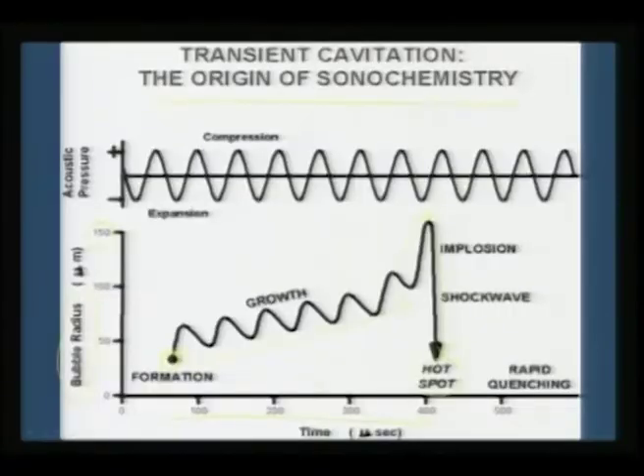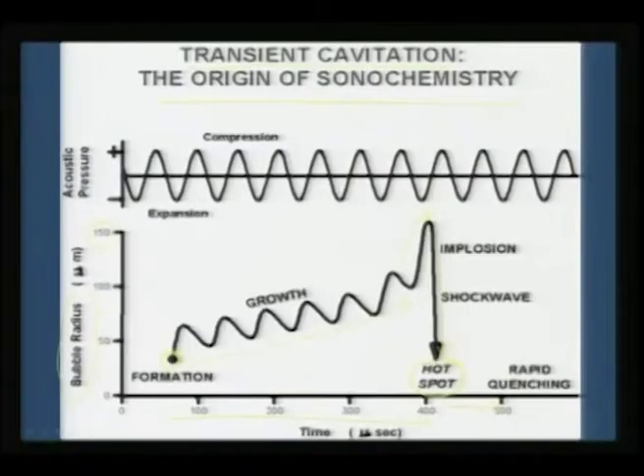At this point when it implosively collapses, very high temperatures and very high pressures are released, and there is also immediately a rapid quenching. Therefore whatever pressure is realized, whatever temperature is realized, it is felt only for a microsecond. So whatever chemistry has to happen has to happen in that microsecond time scale. These are fast quenching, high temperature, high pressure reactions. So the origin of sonochemistry is this transient cavitation, which is implosively